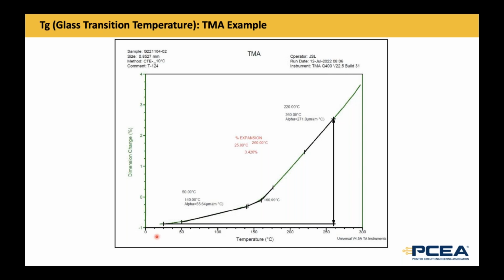The reason that matters is that as the length of the chains of the polymer get shorter, the flexibility of the plastic part of our material goes down. So the way I think about it is if you have a rubber band, it's very flexible, but not very strong. And if you have a piece of steel, it's very strong, but not very flexible, at least over the range of forces that we use. And those two are way extreme. They're way outside of what we make. But in that plastic range, the glass dominates in the XY and the resin dominates in the Z.